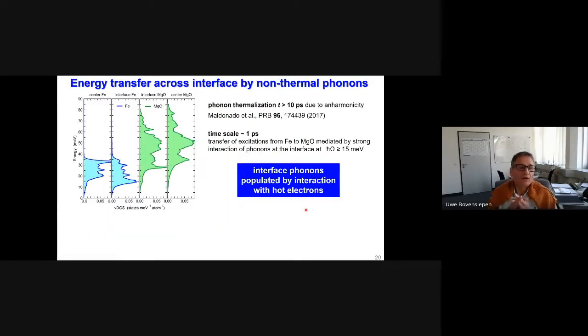So we can now look a bit more in detail into the phononic density of states. So this is what is plotted here, the vibrational density of states as a function of energy. This goes here from 0, these are acoustic modes, and then you have some higher frequency modes up to 35 millielectron volts in iron. And this is here now in the bulk iron. This is then the interface. Here you have the interface MgO side and the bulk MgO. And what you see at the interface, there are pronounced changes in the vibrational DOS, and we consider here this feature at 15 millielectron volts, which is a clear interface feature. It's absent in the bulk, as well as, for example, this feature here, to be now responsible for this very efficient energy transfer by interface phonons across the interface.